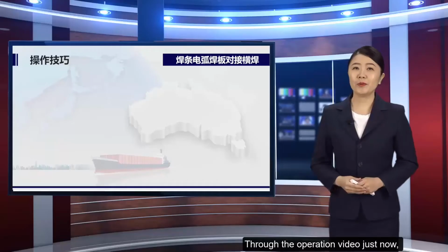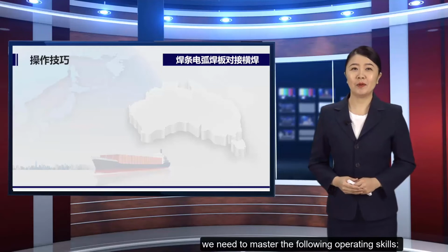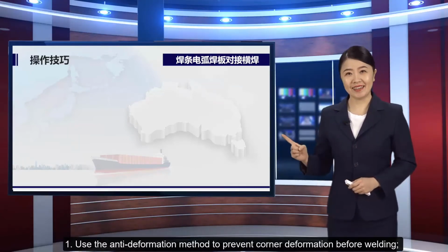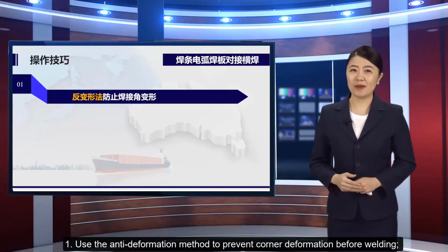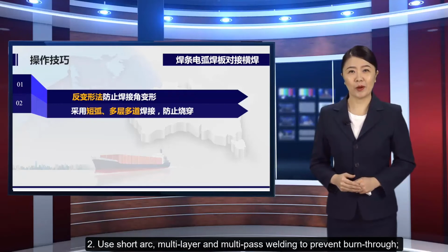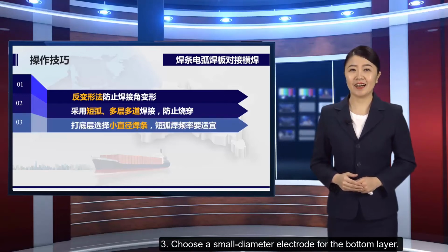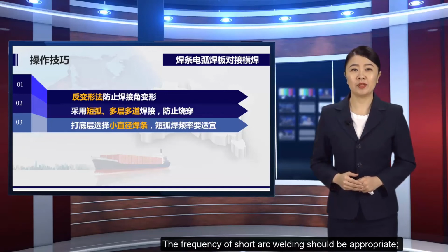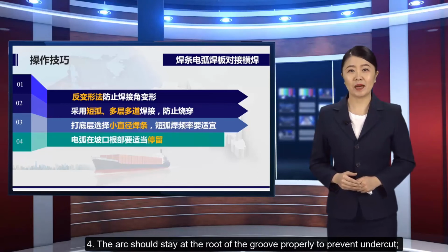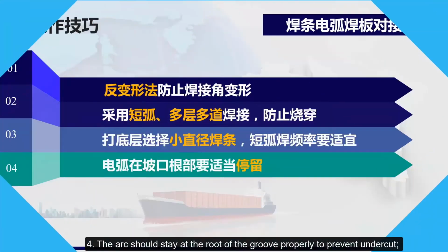Through the operation video just now, we need to master the following operating skills. 1. Use the anti-deformation method to prevent corner deformation before welding. 2. Use short arc, multi-layer and multi-pass welding to prevent burn-through. 3. Choose a small diameter electrode for the bottom layer. The frequency of short arc welding should be appropriate. 4. The arc should stay at the root of the groove properly to prevent undercut.